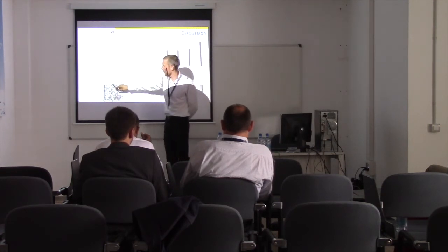And finally, we also did 3D laser profile analysis. So after the recoater deposition, you can see that from a previously melted layer, you have a light intensity variation, which enables us to see that there is an edge effect, a strong magnifying effect here at the beginning and at the end.